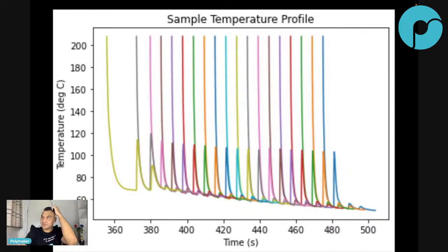Does that make sense? If you have an ABS cube and you try to make the whole thing at the same temperature, don't use a heated bed, don't use an enclosure, use a cooling fan so that the temperature from the nozzle doesn't spread. Then if someone can explain to me why the thermal shrinkage has something to do with an ABS part that is completely the same temperature everywhere, then yes, we can start talking a little bit more about that theory or hypothesis, because for me it's not a theory, at least not from what I have seen.